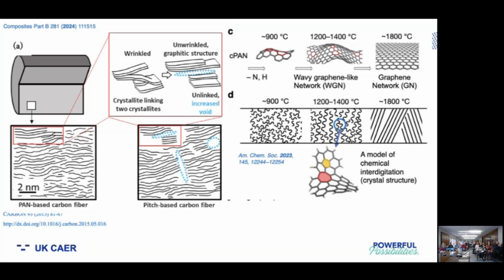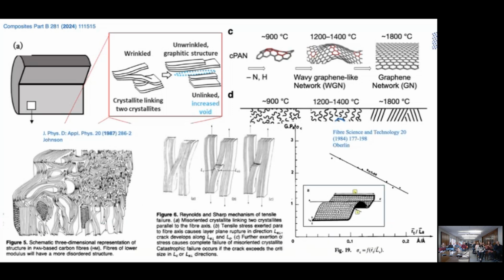And the constituent basal planes are wrapped into each other. This was actually known in the 80s. I'd like to point out one of these papers from the Oberlin group of France, which described, after pretty laborious TEM studies looking at the fibers, that as the radius of curvature they observed in the TEM of these basal graphitic planes became tighter and tighter, the strengths went up.